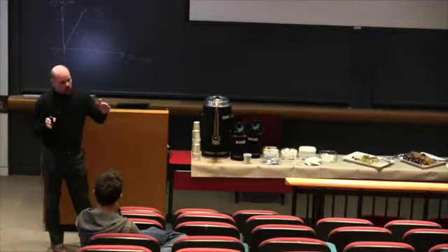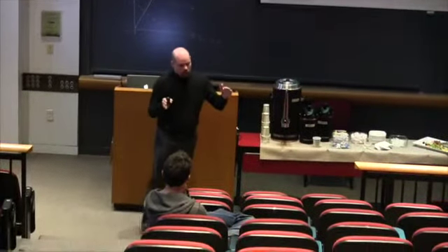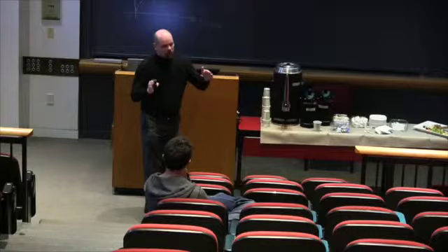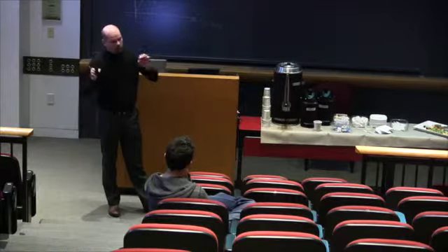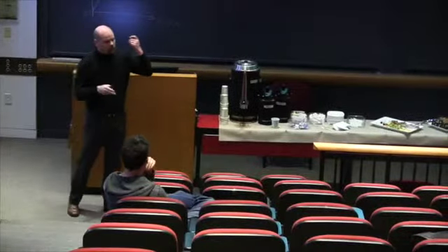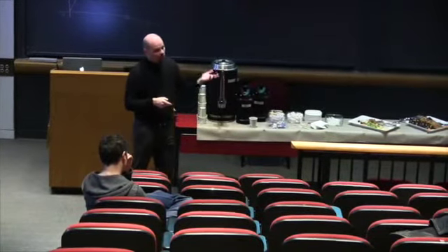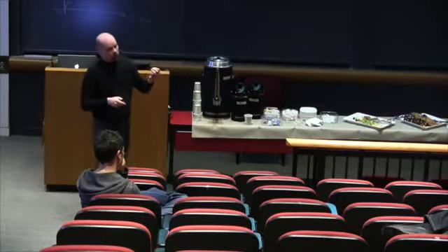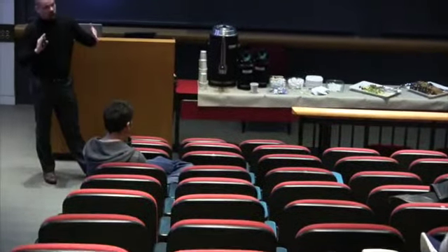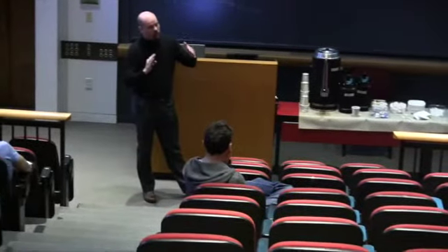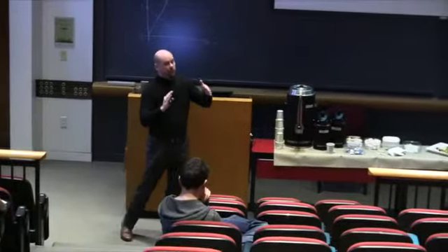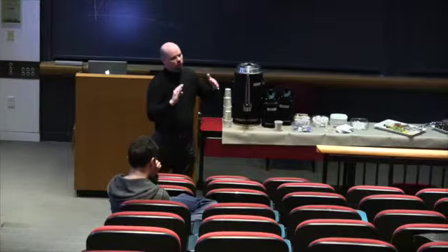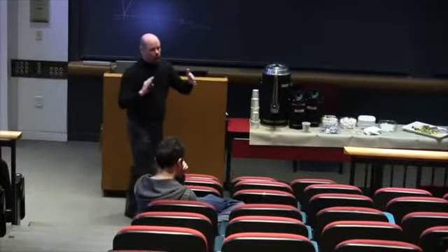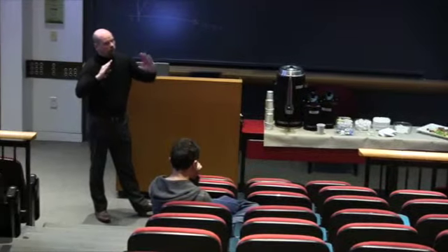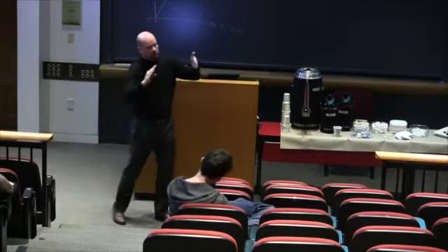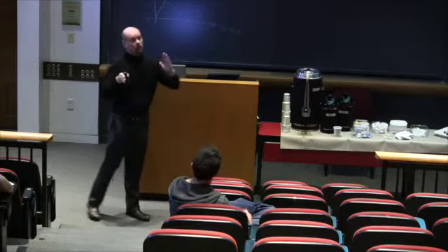And what you can do, actually, I didn't point it out, is look at polarization dependence. If the polarization in and polarization out is the same, it means that the photon has not lost any angular momentum to the system, which means it cannot have made a spin flip. If you are in cross polarization, any excitation that the photons have picked up has to involve some transfer of orbital angular momentum, or angular momentum, to the system. So in an ideal world, if you were able to measure the outgoing polarization, you would see the spin flip disappearing with parallel polarization and popping up with crossed.